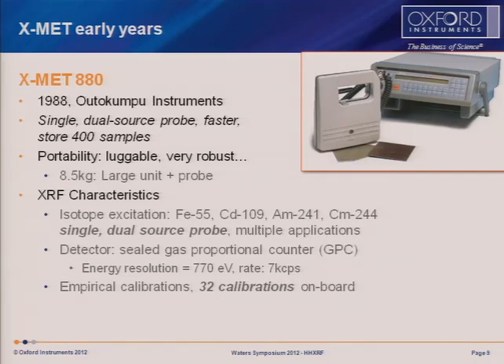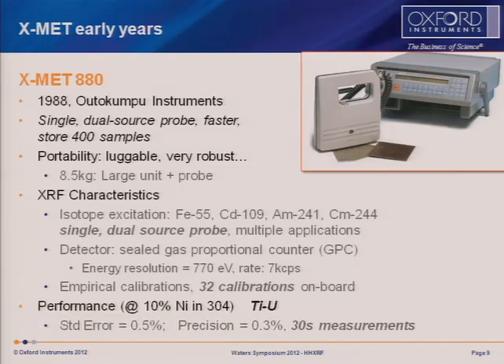out. Getting 6 elements simultaneously from spectra where you cannot discriminate one atomic number from the next is incredibly difficult, but it is possible. It takes a lot of empirical calibrations, and if you want to do really good work, you need a lot of them, and this one said, okay, we need 32 on board now. So electronics are playing the part, but still the performance is not improving much, although the measurement time is actually halved now. So we're beginning to recognize that speed is important as well as portability.